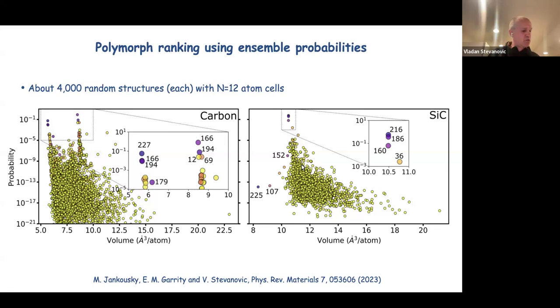Two questions come to mind from this slide. The first one has to do with the fact that the rock salt, which is shown here for silicon carbide, is a known high pressure phase of silicon carbide. And it shows up in this distribution at a very low probability. The reason for this is that now we are bringing energy into the picture, and the probability depends exponentially on the energy. The energy difference between the rock salt and the zinc blende ground state is relatively large. So that's why the probability tanks, especially at room temperature, for the rock salt.